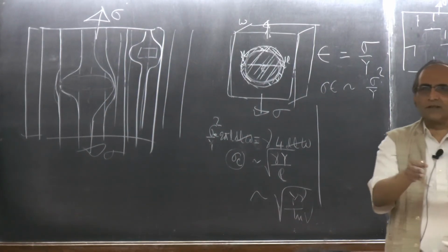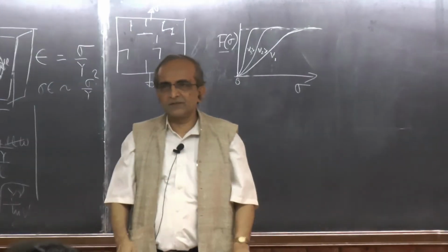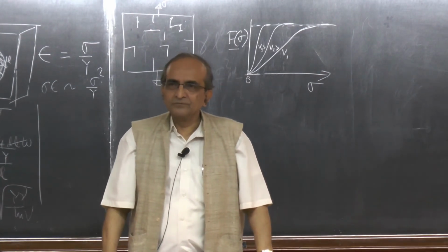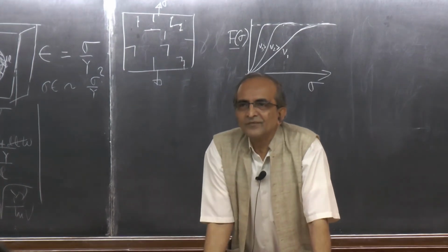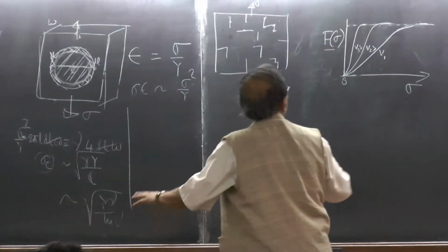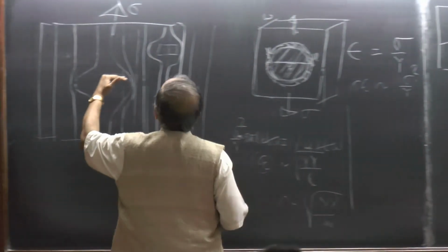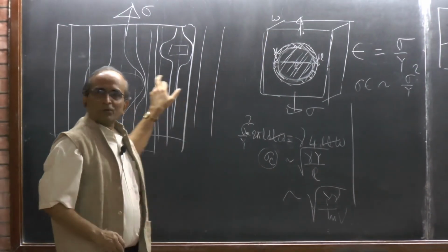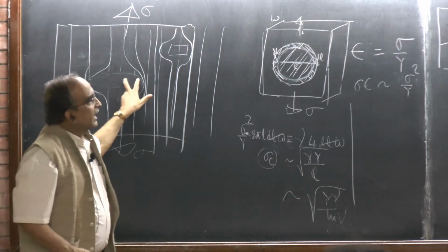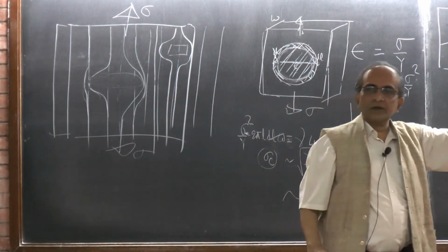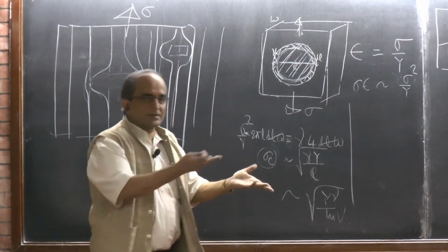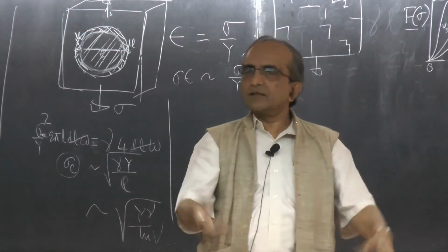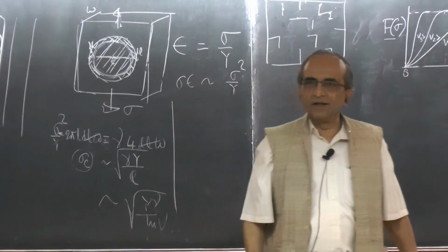And this is what the engineering textbooks, when they give the Weibull and Gumbel distributions, actually show. If you put it there, you will get that. I was confused because I thought for one crack it will depend on volume. No, the idea is like this. In this sample, there would be this one, other one. I want to find out the biggest possible one. And I find that would depend on log L. The biggest one, as you had seen, was responsible for the first breaking. After that the sample is broken anyway. Why do you care for the rest of the group?